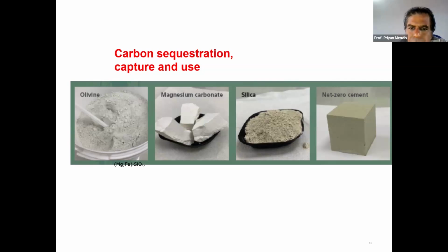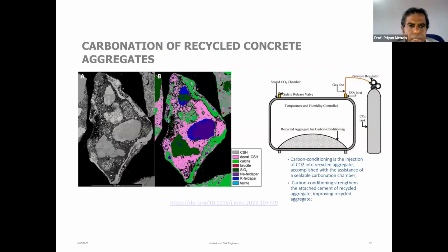So that's something for the future. I can really talk for hours on these different techniques, but I will go to one last slide and stop there. Recycled concrete aggregates: another thing we are doing is passing carbon dioxide through the recycled concrete aggregates. Recycled concrete aggregates are weak because there are two layers. One is an old cement layer, the other is a new cement paste layer, so there's a weak layer around the aggregates. For those who want a bit more detail, that is the weakness. That's why we can't use too much recycled concrete aggregate.